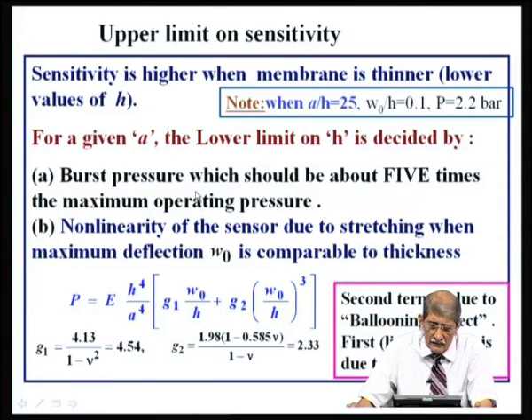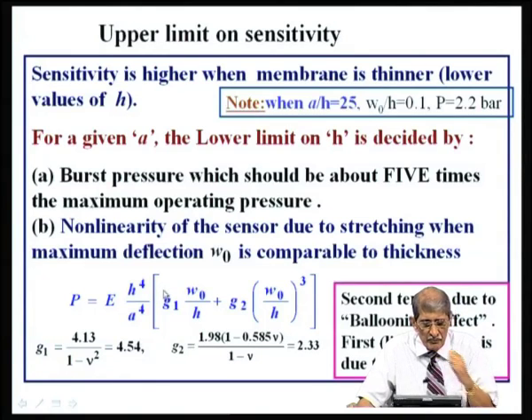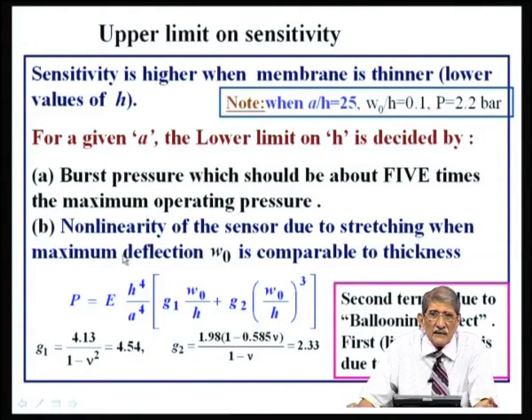See, there is a relationship based on the theory of plates. The pressure is related to the deflection W naught divided by H by this relationship. A by H is the membrane dimension. Okay. So, if I keep A constant, if I keep on reducing H, this equation tells you that first term is linear, W naught by H is linear. If second term is negligible, the pressure and deflection are linearly related. So, your delta R by R or the sensitivity will be linear function of pressure. Okay. If you increase the pressure, the output voltage will increase linearly.